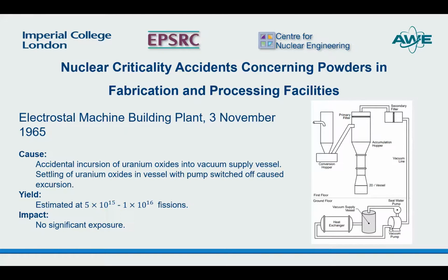However, typically there are 2 filters, you can see a primary and secondary filter there, but at the time of the accident, it was found that due to operational mistakes, the primary filter was missing and the secondary wasn't fitted correctly.